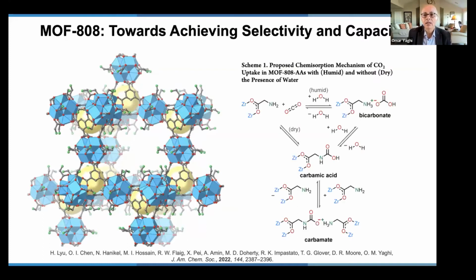Now, what we find is that as you are binding CO2 from humid air, in the presence of water, you make this bicarbonate ion pair. And this is operational when you have a lot of CO2. So let's say if I'm binding CO2 from flue gas, this is what I'm going to make. I'm going to make this unit. And notice that bicarbonate is part of what you make. And this is a very unstable molecule and does not require any heating to remove the CO2. You can just pull vacuum on this system, as we have shown in this recent paper, to remove the CO2. So that's the kind of control that one can have inside the pores.